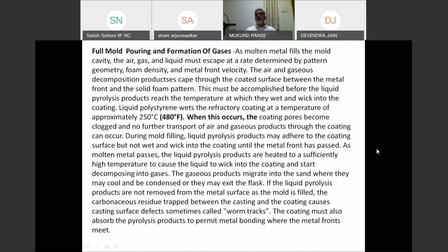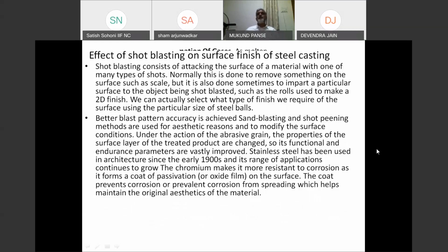You have to avoid the liquid pyrolysis product, which is a carbon film, liquid carbon film or tar, accumulating. For this to stop, the gas formed should pass through as fast as possible. That's why the permeability of this coat becomes very important in this case. This is to get the basic surface finish of the casting.